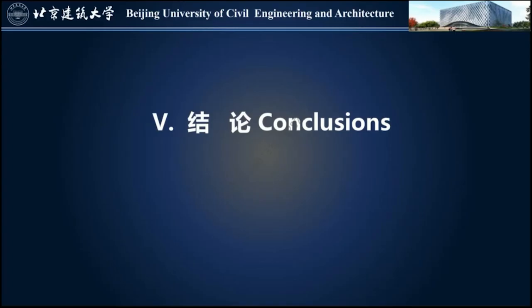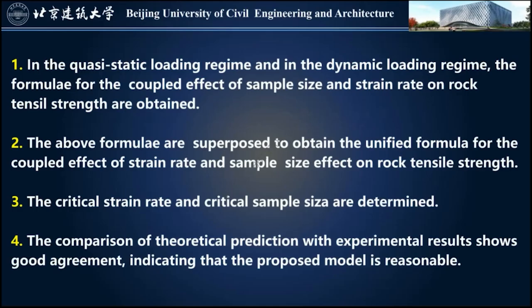Part 5. Conclusions. In the quasi-static loading regime and in the dynamic loading regime, the formulae for the coupled effect of sample size and strain rate on tensile strength are obtained. The above formulae are superposed to obtain the unified formulae for the coupled effects of strain rate and sample size on tensile strength. The critical strain rate and the critical sample size are determined. The comparison of the theoretical predictions with experimental results shows good agreement, indicating that the proposed model is reasonable.